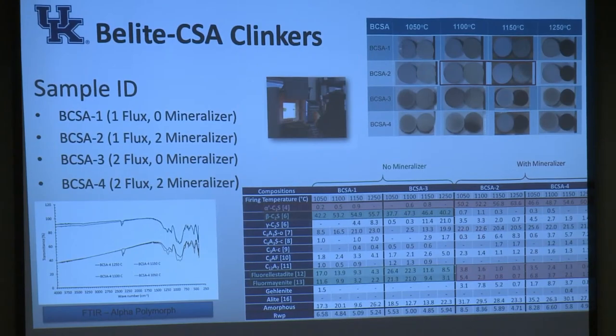That's its manufacturing temperature. Now it'd be Belite CSA, so that's calcium sulfoaluminate cement. Portland cement, if you think of it, when it hydrates, the glue, the binder, is a gel, calcium silicate hydrate gel. CSA has a phase in it called ye'elimite, which hydrates to form a hexagonal crystal called ettringite. So you can think of a Velcro structure. That's where it gets its strength, and it kicks off fast. It's a fast reacting cement, and it's strong. So that's why we coupled that slow horse, the Belite, which DOE wanted, had some belief that provided the durability, with the high strength CSA part.